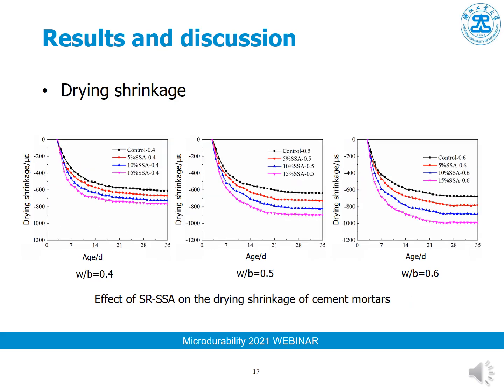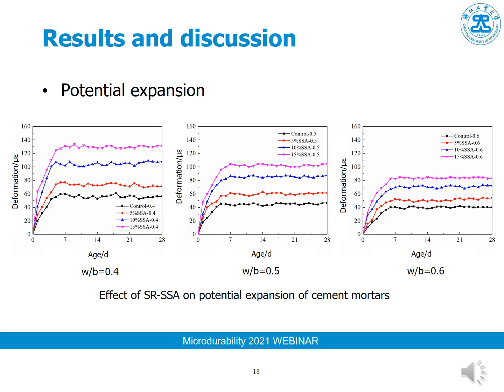This is the test results for the drying shrinkage. And we can see that with the addition of sewage sludge ash, the drying shrinkage of the cement mortars was enlarged, and more sewage sludge ash caused a much higher drying shrinkage. For the potential expansion, we can see that if all the specimens were immersed in the water, they all expanded, and also more sewage sludge ash caused more expansion.